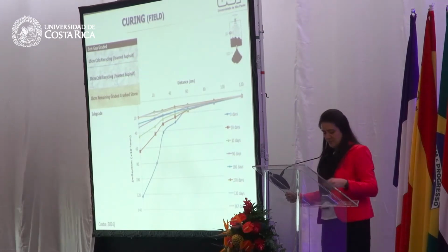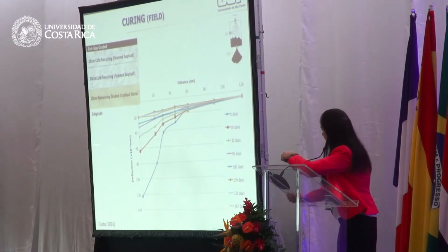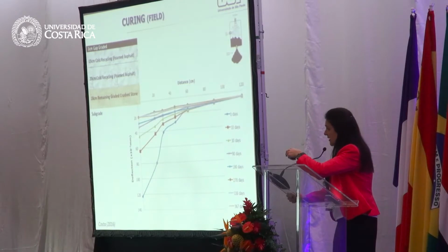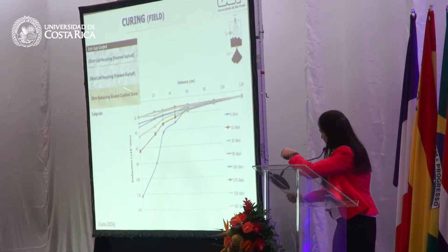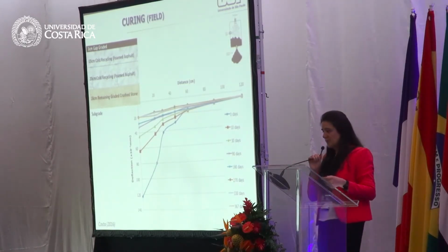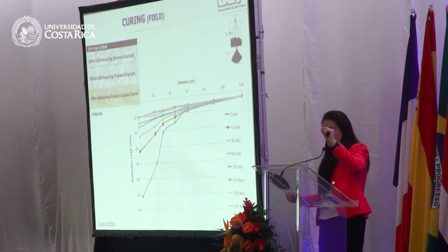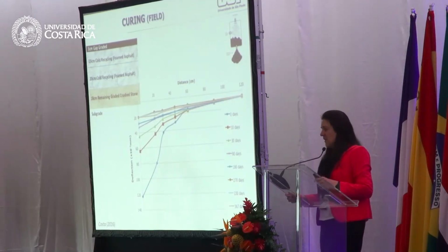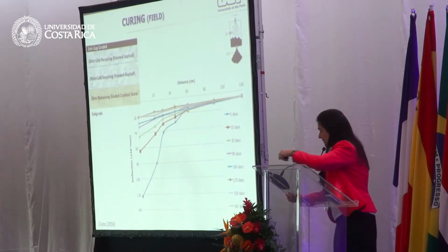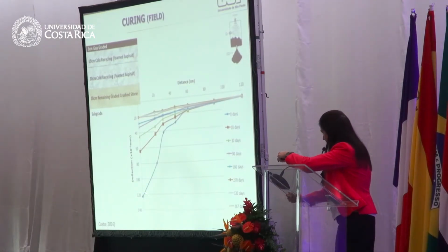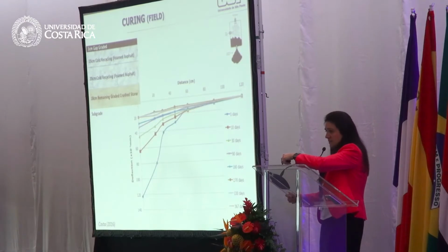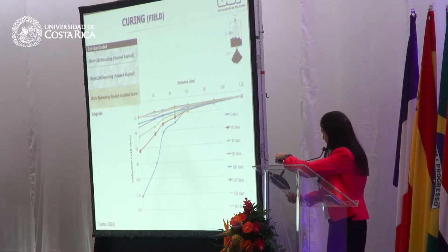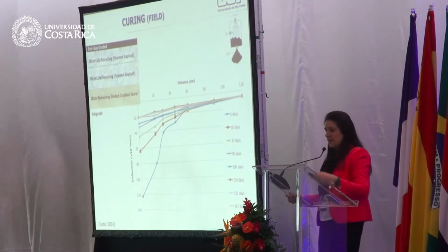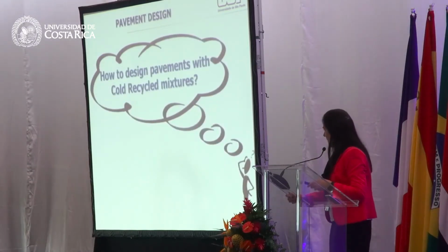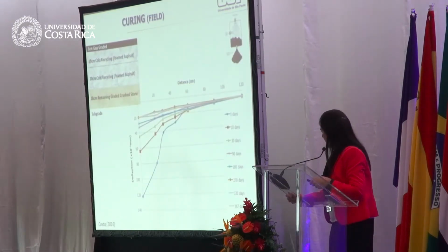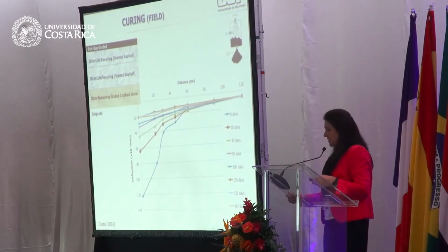In this chart, this is a very emblematic chart. We have here the pavement structure after rehabilitation. So we have these two layers of foamed asphalt recycled mixture and just 3 millimeters of cap graded. And we see here, it starts at 120, the maximum deflection, and it went down until 20 with time. This one was after a little more, or almost a year.